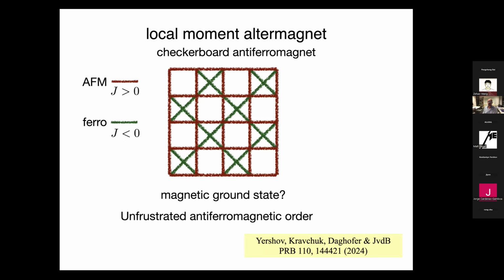Now let's consider an altermagnet, and this is the simplest altermagnet that I could come up with. It's a checkerboard antiferromagnet, where again I consider local moments, so local spins. And I considered this checkerboard with antiferromagnetic interactions between nearest neighbors, as I did before, and now added ferromagnetic interactions between next nearest neighbors along this diagonal on every second plaquette. So this is the checkerboard nature of this model. And I could ask you, what is the magnetic ground state of this checkerboard antiferromagnet?